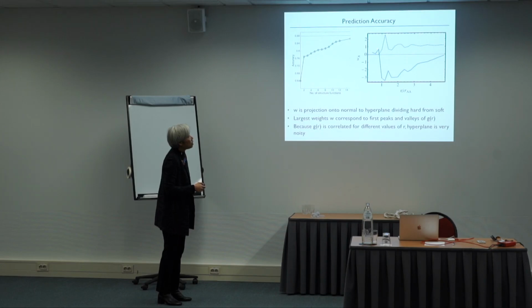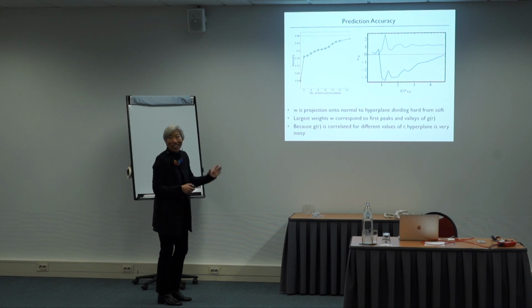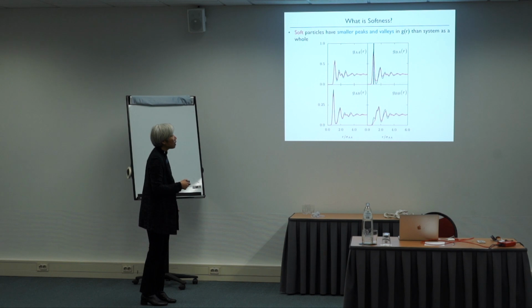Then I look at the weights. This is g(r), and this is the weight. This is what the average g(r) looks like, and these are the weights. You see that it's large in magnitude at the first peak and at the first valley, and it gets smaller as you go further away. In the end, this turns out to be the difference between soft particles, on the soft side of the hyperplane.